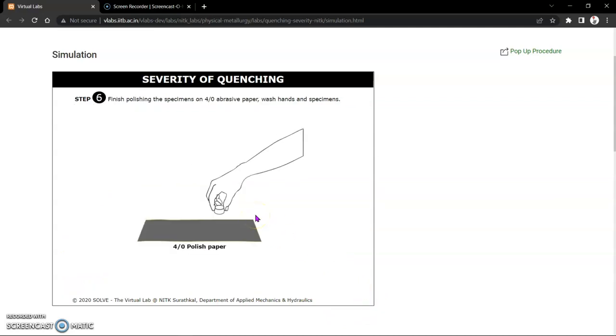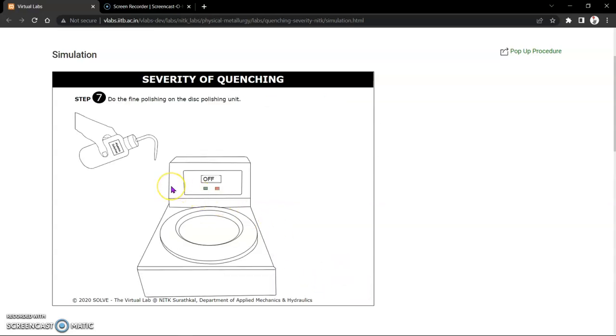Step 6. Finish polishing the specimen on 4/0 abrasive paper. Wash hands and specimen. Step 7. Do the fine polishing on the disc polishing unit. And this is the alumina solution. After that we can start polishing.